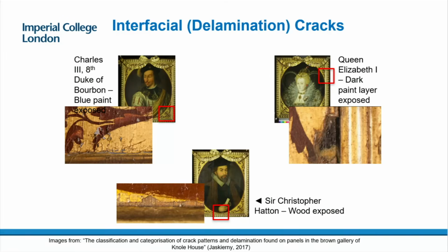Why we care about the temperature and humidity fluctuations: these paintings are made out of different layers of paint. When the humidity changes, each layer wants to expand by a different amount. It starts pulling on the other layers next to it, and that's how cracks form. Of course, this pulling is very small, but if it happens continuously over a very large number of years, then eventually you get fatigue, and this is what causes the cracks. So there's two types of cracks in such paintings. This is the interfacial or delamination cracks.